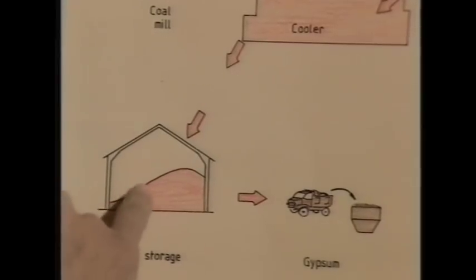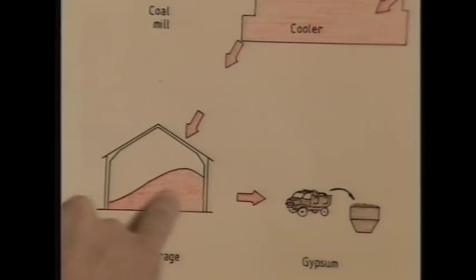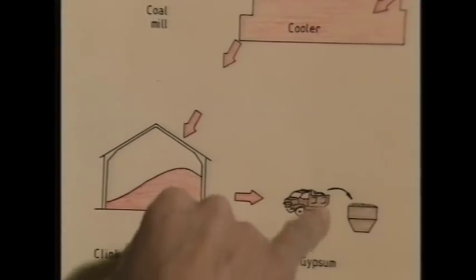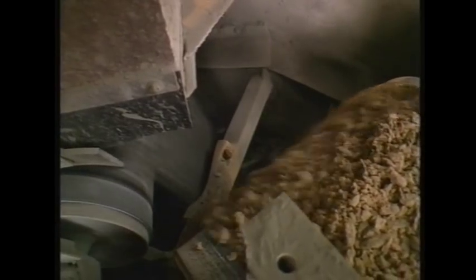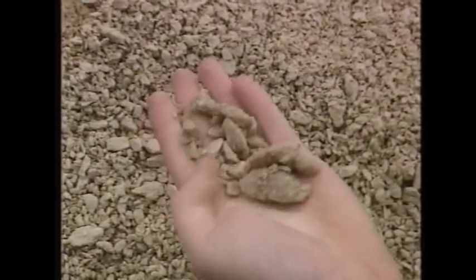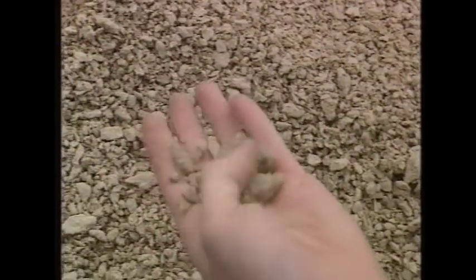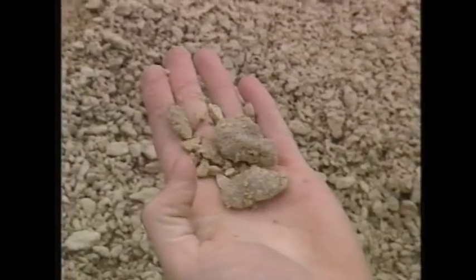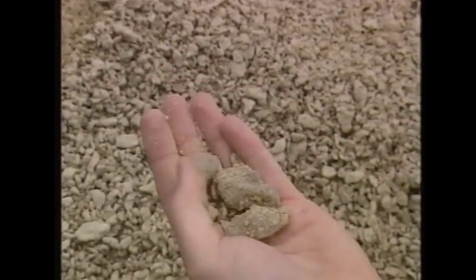At this point, we extract from underneath the clinker shed via vibratory feeders, and we add in approximately 5% of gypsum. The purpose of the gypsum in the clinker gypsum blend is to act as a setting agent. It's worthwhile to note that at every stage of manufacture, this is the only time at which we introduce a material that is not locally won here at Kandos.